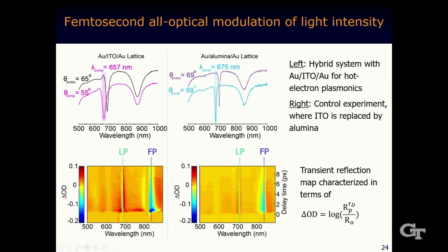So the optical modulation of the light intensity is characterized by using a pump-probe scheme. We have a broadband probe light, and then we shoot the pump light onto the structure, which modifies the electron distribution. Then the probe light will probe the structure, and the change in the probe light is characterized by the transient reflection mapping.